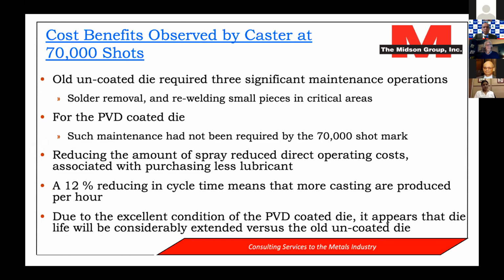Clearly reducing the amount of spray you use reduces cost because you can purchase less lubricant, and lubricant is not inexpensive. Improving the cycle time means that more castings are produced. Obviously that affects costs. But probably the biggest one is that the PVD coating, the reduced spray, appears to offset heat checking, and therefore will get a significant increase in die life.